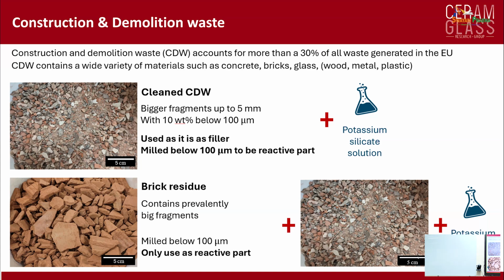You're also familiar with the fact that they're fired at low temperature, around 880 degrees, at least in Italy, which means that you still have a large amount of reactive amorphous aluminosilicate. So brick residues work very well for making geopolymers. And you can use cleaned